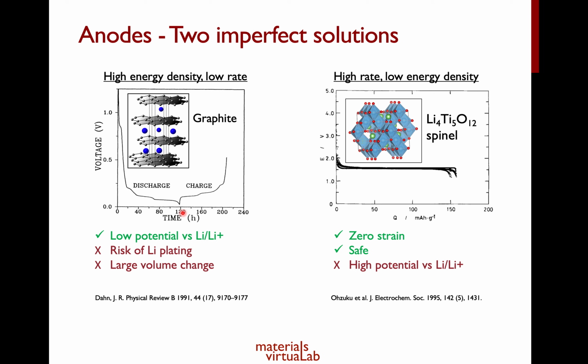However, the low potential versus lithium plus is one of the reasons why graphite is limiting in other applications. When you cycle graphite too fast, you run the risk of lithium plating, and that carries with it a significant safety risk. Graphite also experiences relatively large volume changes when you cycle it, again contributing to cycling stability and safety issues. Graphite essentially is what is known as a high energy density but somewhat low rate material.